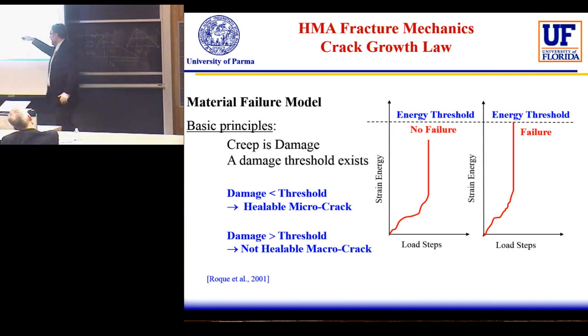So in the basic concept, if you are below the energy threshold, the healing is able to seal the micro crack. If the strain energy goes above the energy threshold, the healing is not able to heal the cracking, and we have damage. So, a not healable macro crack. Following this approach, we can define the micro crack when we are below the threshold and the macro crack when we are above the threshold.